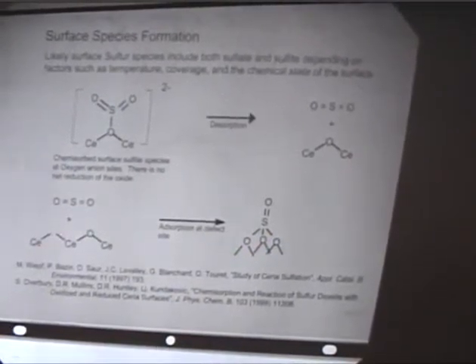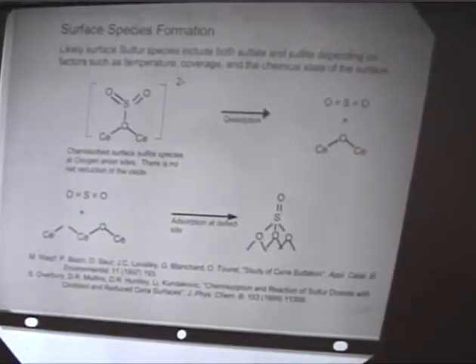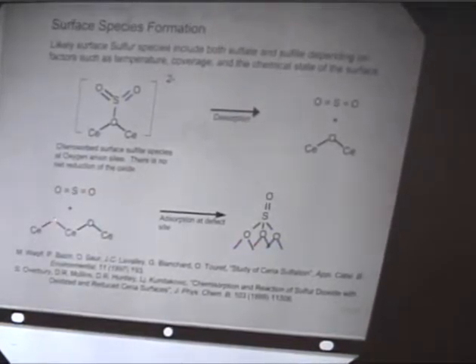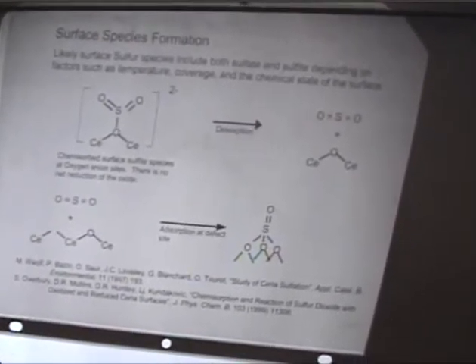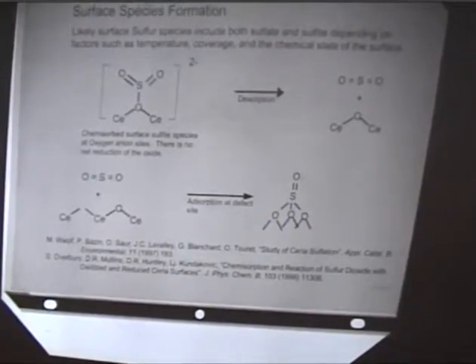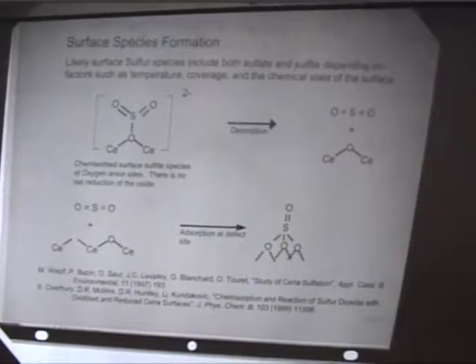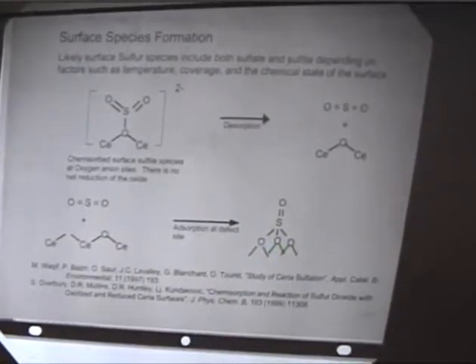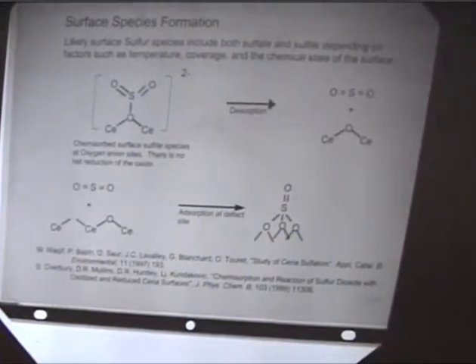And we think that this could be occurring at these places where you have these oxygen vacancies. So the oxygen group comes down, and then you have some sort of magical bonding configuration that happens. Like I mentioned before, this has been observed in IR. This sort of thing has also been observed in IR. The XPS results are confusing to say the least, because it involves lots of peak fitting, and you can probably make it whatever you want depending on how you fit your peaks. However, we are looking at both of these particular species right now in follow-up XPS experiments that I hope will eventually give us a better model for what is occurring.